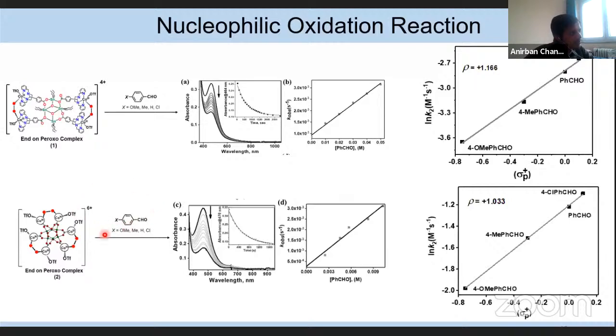The same kind of experiment was also performed with hexanuclear peroxo species, endon peroxo species 2, where the decay of the 470 nanometer band was observed, and from the different k2 values when we plotted, we found the positive Hammett constant value, which confirms its nucleophilic behavior.